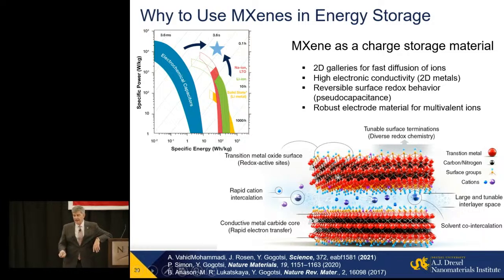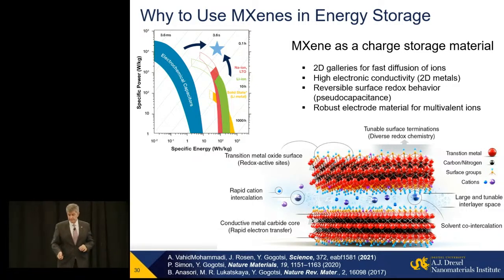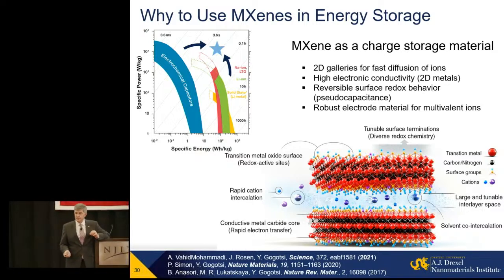They have high electronic conductivity, even if you do surface redox, it stays. They have on the surface molybdenum, vanadium, niobium, titanium, actually many of the same elements that are used in current battery materials. Transition metals have different degrees of oxidation and can change their oxidation state. You can change the oxidation state of elements on the surface without disrupting the structure. There is no phase transformation happening. They also have channels for transport of ions between the layers, and all active elements are on the surface, so there is no solid state diffusion.